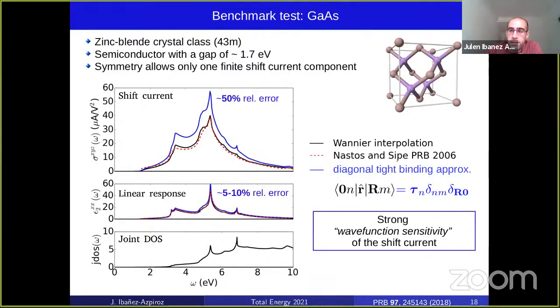And how can we do that? Well, because of the formalism, we can switch manually off the diagonal matrix elements of the position operator. We can refer to this as the diagonal tight binding approximation, because in tight binding, those terms are not considered. So the result of doing so is shown in blue. For the linear response, we see that it doesn't do much. So this means that those terms are not important for the linear response.